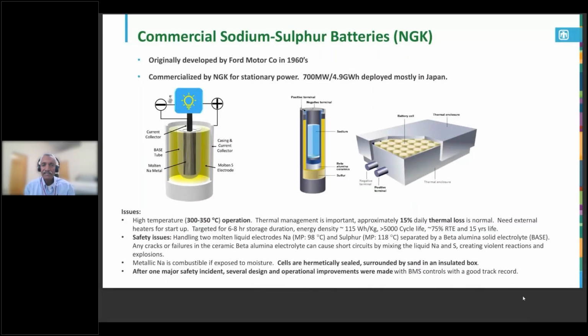So NGK developed these batteries commercially. They're selling them. So far, 700 megawatts or 5 gigawatt hours are deployed, most of them in Japan, and there are some deployments also in the United States and Europe. As we discussed, this is a high temperature operation, right? 300 to 350 degrees C. So thermal management is important in these batteries. You lose about 15% of the heat due to thermal losses. It's typical. And you need an external heater for startup because initially you need to bring it to the temperature. Once it is running, then you don't need to supply any more heat.